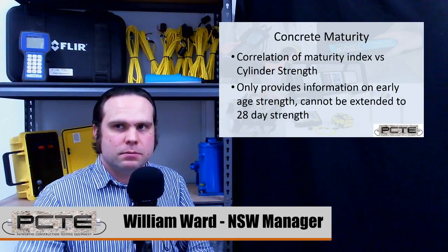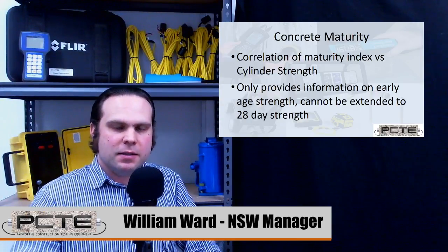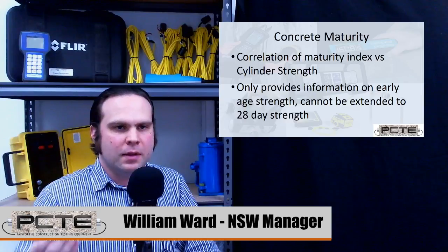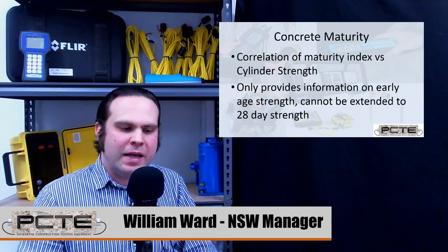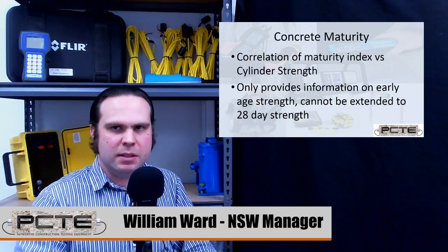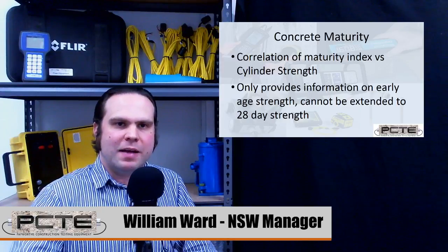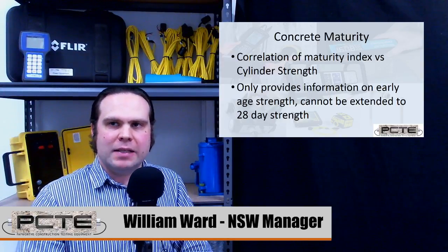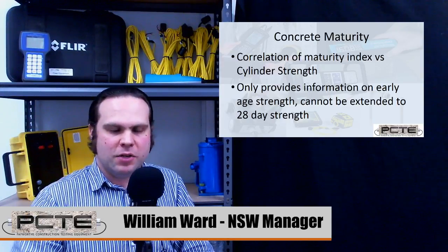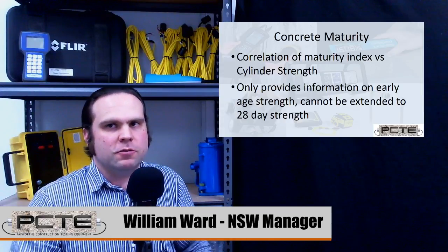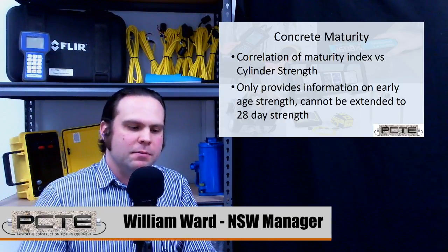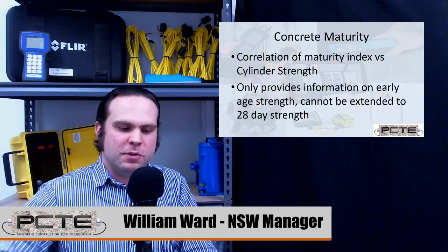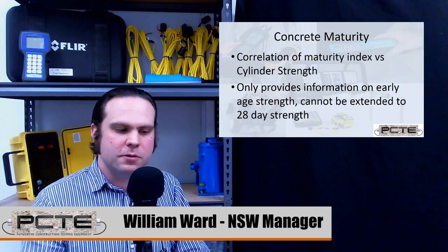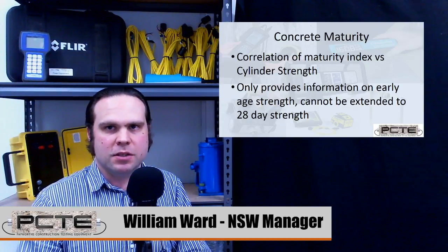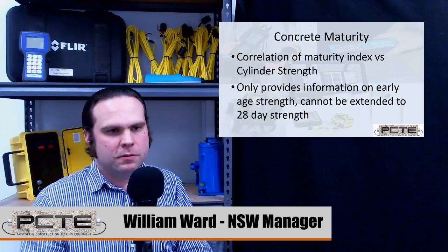In either case, we watch the increase in index as time occurs, and that index will inherently take into account the temperature change in the material. Once a certain value is reached, we'll check that versus our strength relationship and read off a strength from the graphs. Now, the other key thing to be aware of with maturity is that it is used as an early age strength relationship. It's not a replacement for a cylinder strength.